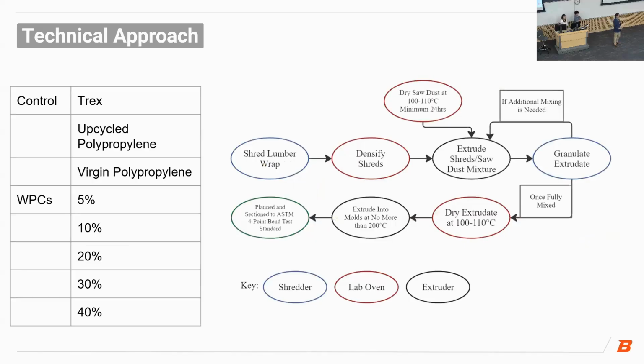The specific way in which we tackled this approach was by having 3 control groups and 5 variable samples. This allowed us to compare the wood plastic composites that we manufactured to an industry standard, to an upcycled polymer that did not contain any reinforcement, and finally to a virgin polymer, polypropylene, so we could evaluate the impact that upcycling might have had.